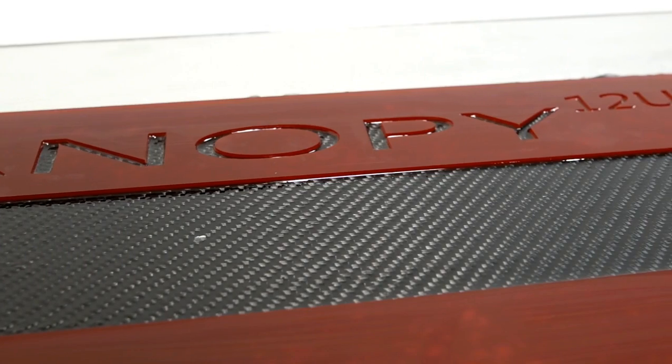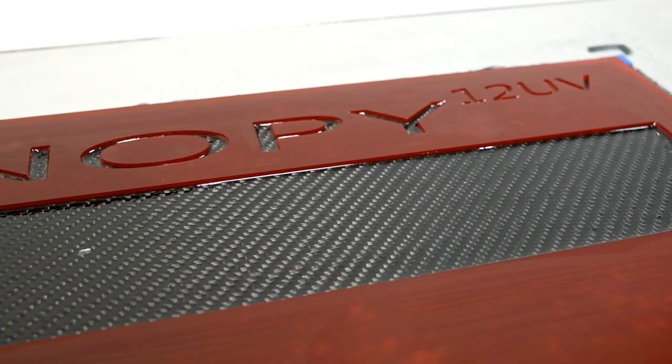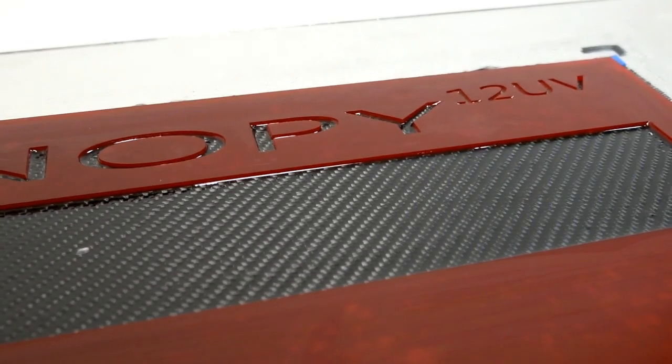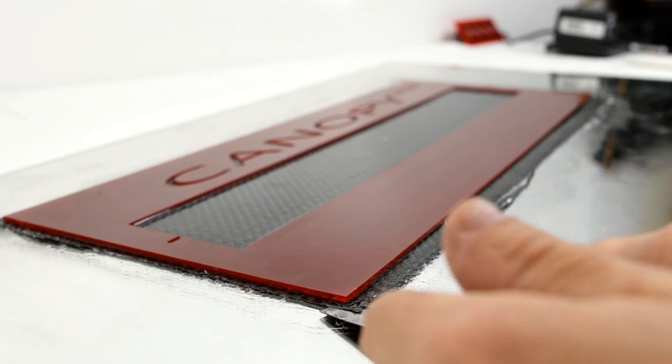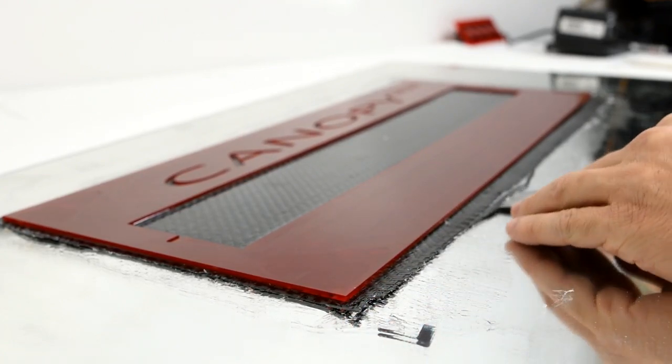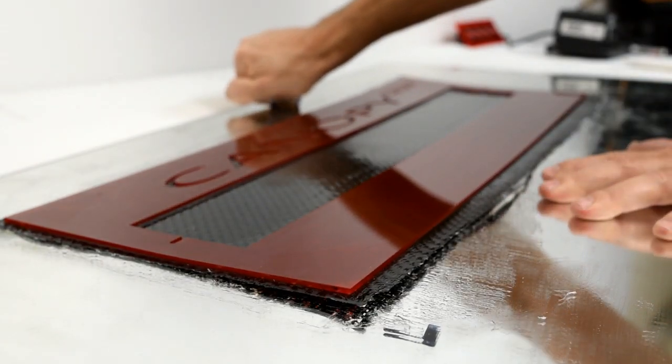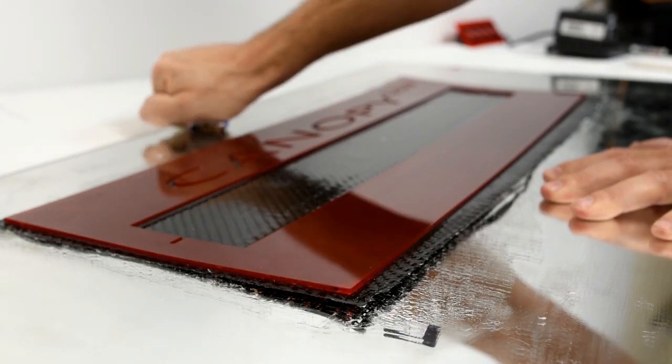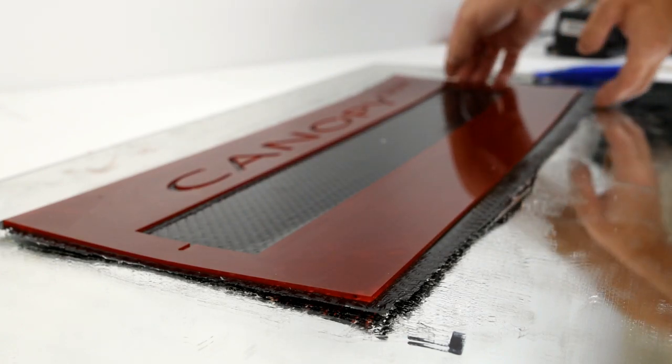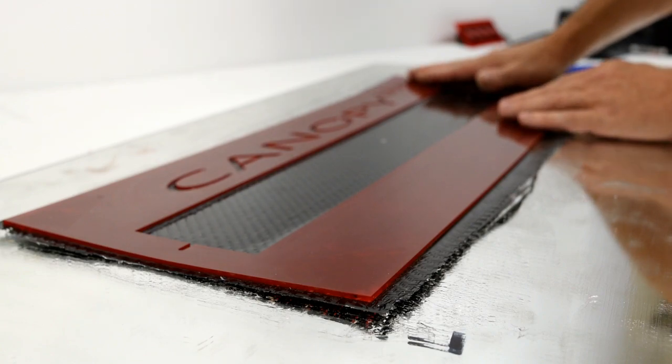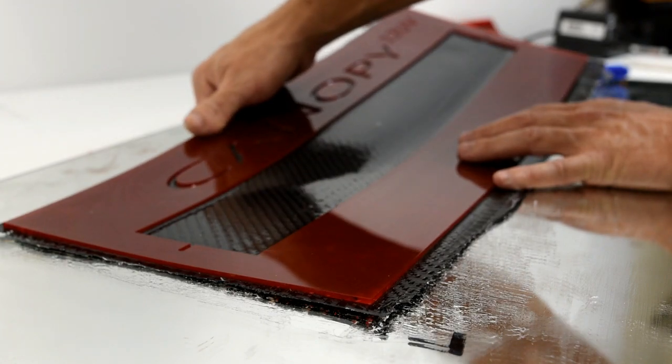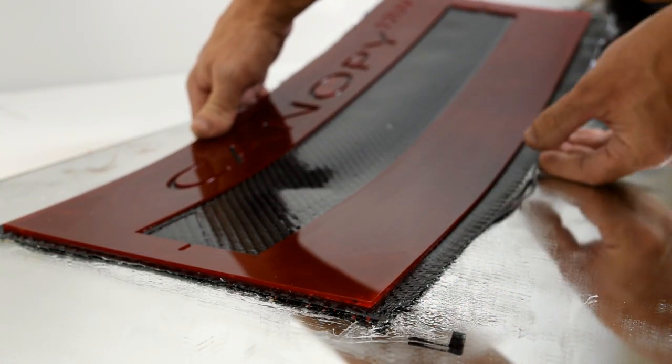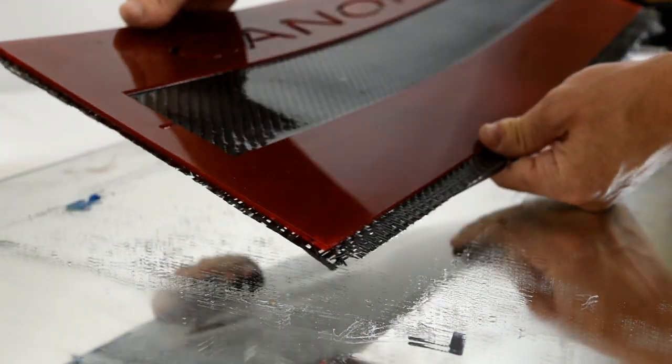So I went ahead and vacuum bagged it, not shown here, and was like okay dope, like no air bubbles, it looks cool, I'll cut this thing out and we'll have that carbon fiber element pulled into the front side of the panel. All good. But when I went to release the mold from this mirror, I did the layup on a mirror, the whole thing basically just fell apart on me. I had sanded the back of this thing so that the resin would adhere to the acrylic but I started getting a lot of delamination at the corner so you could see it through and then it started bowing up on me and it just looked like absolute dog shit. So back to the drawing board on this one. I'll come up with something and I'll release what the final cover panel will look like in the final video.